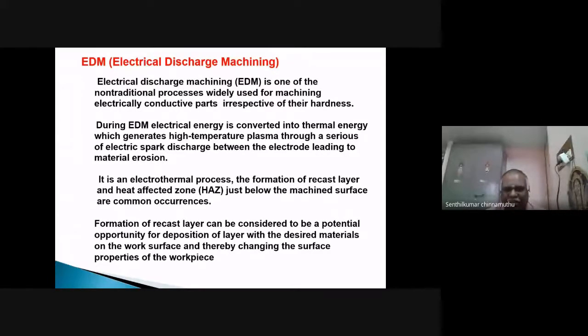If you check this recast layer using EDS element analysis in electrical discharge machining, you might find that the layer consists of tool material, workpiece material, and carbon. Carbon is deposited due to the dielectric cracking. That carbon is deposited along with the parent material as well as the tool material. So if copper is used as the tool, copper is deposited on that recast layer. If brass is used, brass is also deposited along the recast layer along with the carbon and the parent material.